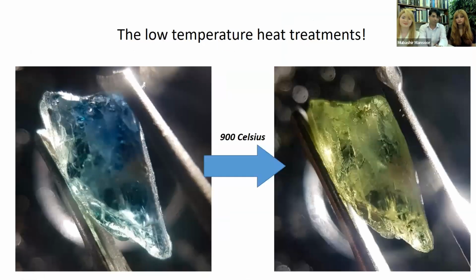Now, from our own treatments, yes, we could see amazing transformations at 900 degrees Celsius, and that is phenomenal. Now, look at the transformation. Since it is a backlit image, it actually shows a lighter color, but this blue is actually quite a dark blue. At 900 Celsius, we not only removed the blue color entirely, but we were able to induce a whole different color as well. And this whole thing happened at 900 Celsius. You send this to a gemological lab, I bet there is a very, very small likelihood that they will be issuing a heated report for this.